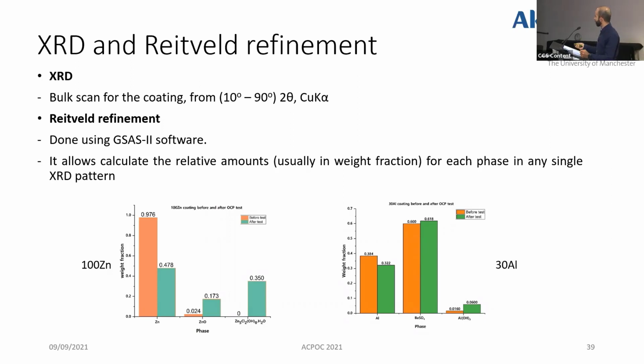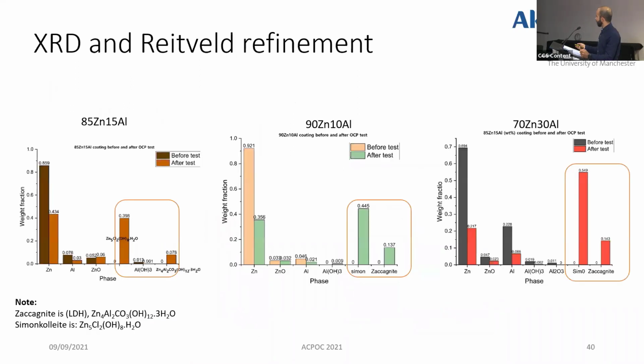But for 30 aluminum, there is almost no reaction or no galvanic action for the aluminum, only some traces of aluminum hydroxide. In contrast, for zinc aluminum coatings, it shows that characteristic corrosion product, which is zaccagnite layered double hydroxide, which indicates that aluminum actually took part in galvanic action and dissolved some part of it to produce aluminum ions with zinc ions to form these crystalline corrosion products that help increase the barrier effect or the barrier properties of